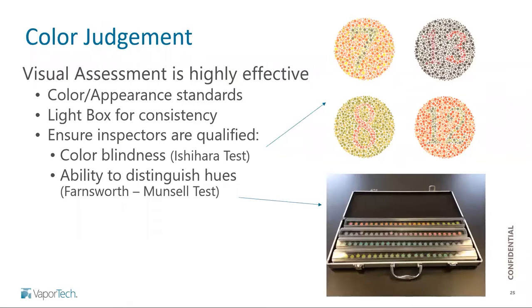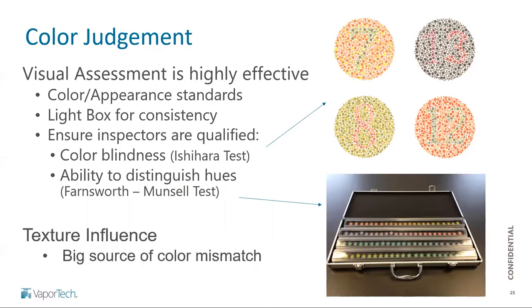Very similar to color blindness is the ability to distinguish between hues. And this is the Farnsworth-Munsell test that we also recommend. This is just a series of little pellets that have varying shades of color on them. The idea is you start these out mixed up and you are to put them in order of graduations of color. So if you can put them back in the right order, that means that you are good at being able to distinguish very fine changes in color hue. So both very, very useful tests to assess your inspectors.